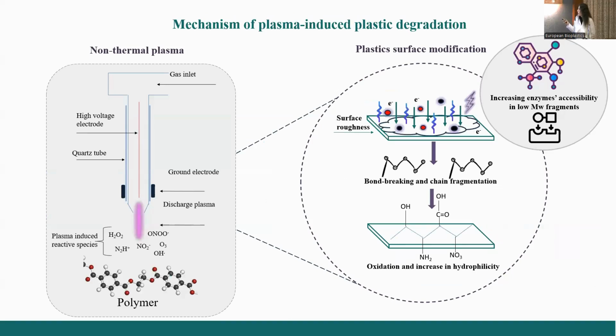In this slide, you can see a schematic representation of the mechanisms of plasma-induced plastic degradation. The process begins when the surface of the polymer is exposed to a chemical-rich environment consisting of nitrogen and oxygen reactive species. By optimizing parameters such as electrical discharges, the gas type that we use in the plasma, and treatment duration, we can selectively modify the properties of the polymer and induce surface roughness and partial fragmentation of the chains. In this way, we can increase the hydrophilicity of the polymer, making it easier for the lower molecular weight fragments to be accessed by the enzymes.